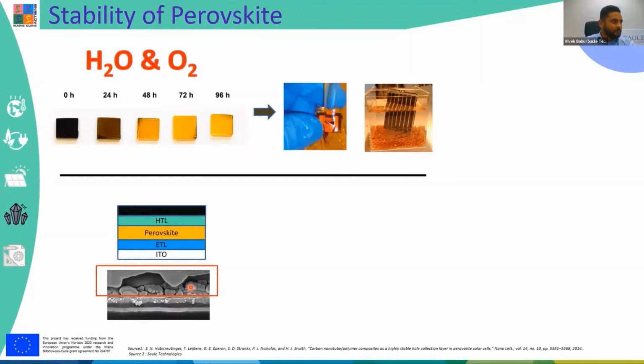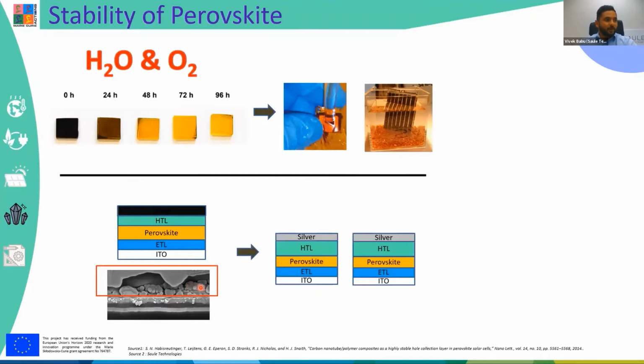And what we can do are two strategies. One way scientists are finding is to have a passivation layer in between, so that it literally blocks those ions from reaching the silver layer. Or the other one is to just remove the silver and use an organic carbon, for example, which doesn't have anything to do with these ions, which is quite cool.